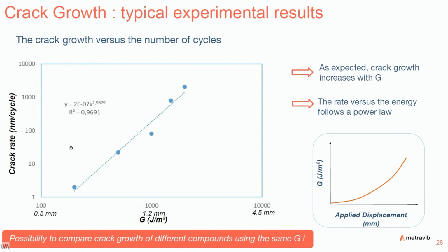Here you have the comparison of the crack growth rate, in nanometers per cycle, as a function of the tearing energy. It's quite simple because, as expected, crack growth rate increases with G. It's quite normal, and the rate versus the energy theoretically follows a power law. You have the coefficients of this law indicated here.